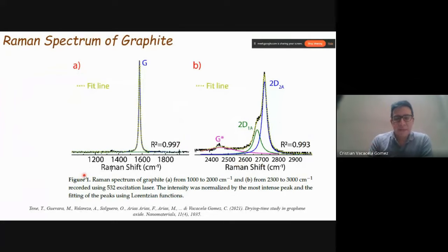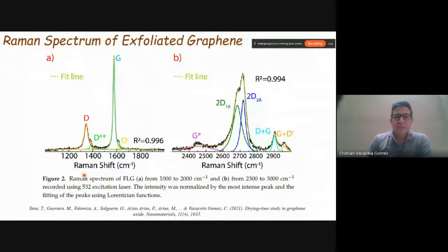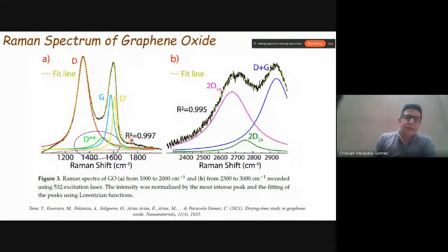Then, just to remember, this is the Raman spectrum of graphite. Now we have the Raman spectrum of exfoliated graphene, where in addition to the G and 2D peaks, we have the D band and the D prime band. And now this is the Raman spectrum of graphene oxide, which is very different from the previous two. We now have an intense D band, but it's not narrow, it is a broad band. Also, in the G band we now have the contribution of the G band and the D prime band. And the interesting thing is that an extra band appears, the D star peak, which we will discuss in a few seconds.